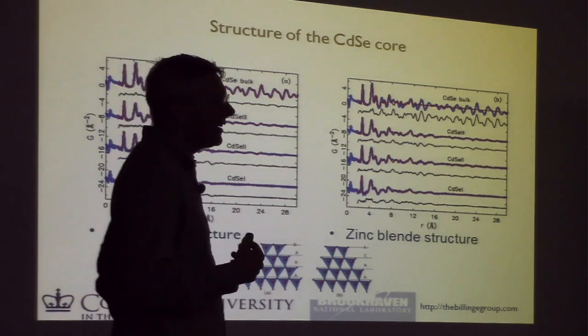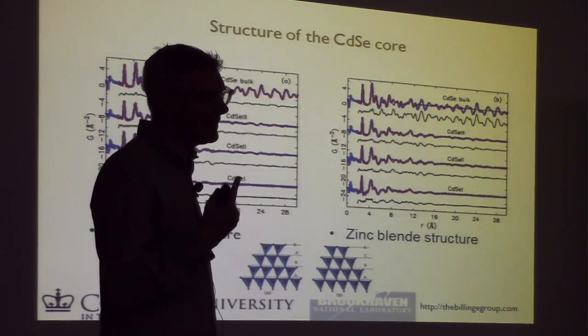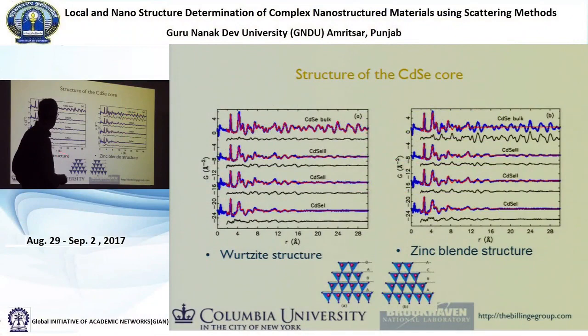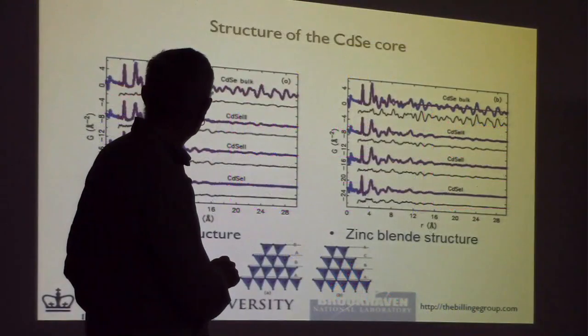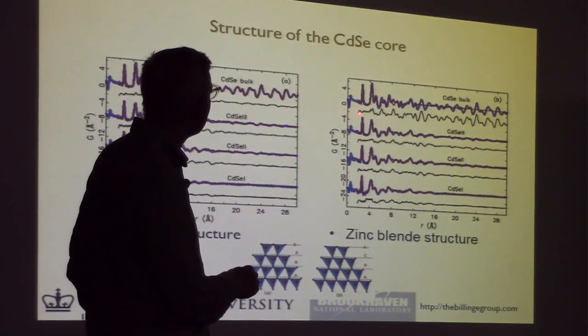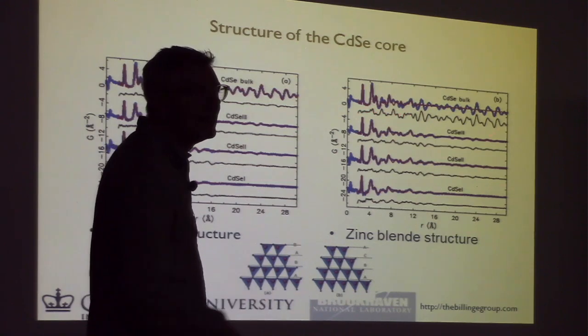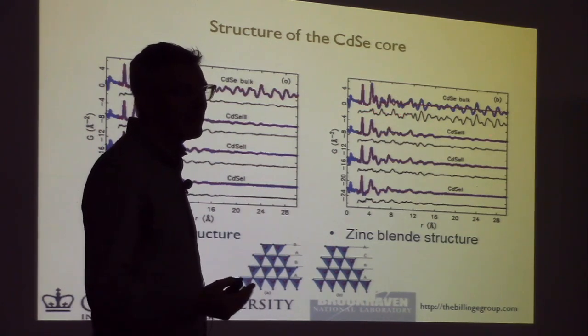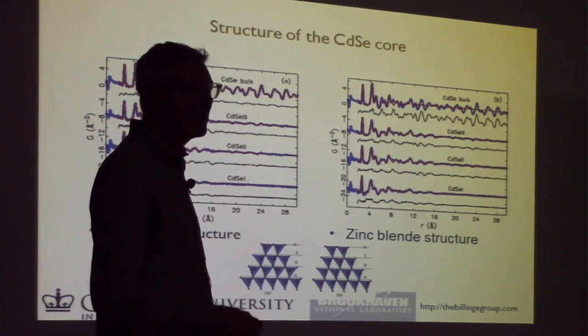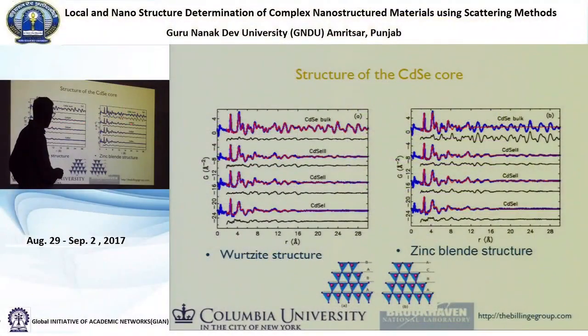And people always want to ask the question, there's two structures that these semiconductors can have. One is wurtzite, and one is zinc blende. This is cubic, this is rhombohedral or hexagonal. And so we ask the question, is our nanoparticle wurtzite or zinc blende? So if we look at the bulk material, the wurtzite fits pretty well, and the zinc blende fits pretty badly. So we can say wurtzite. Done. If we look at the nanoparticle, the situation is not quite so clear.